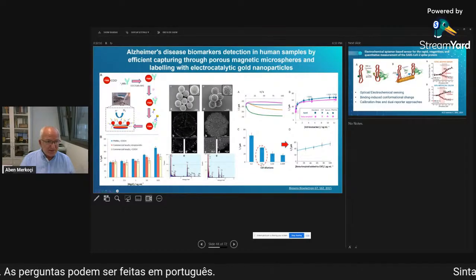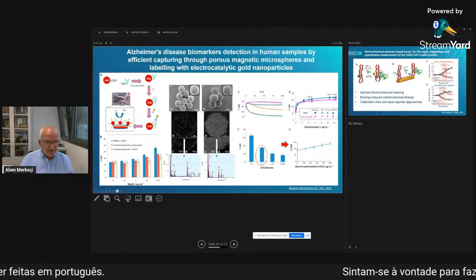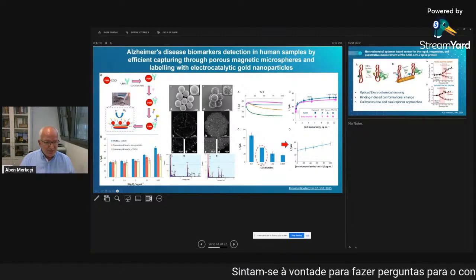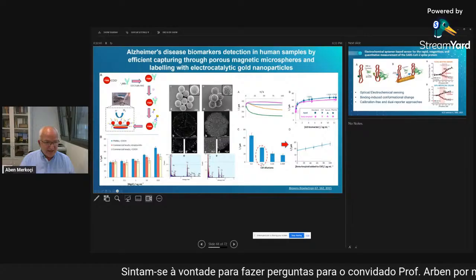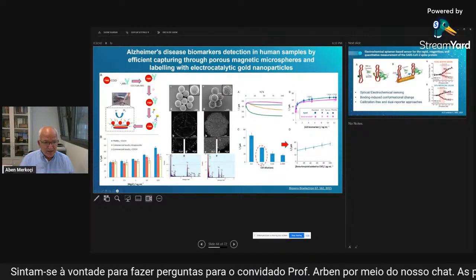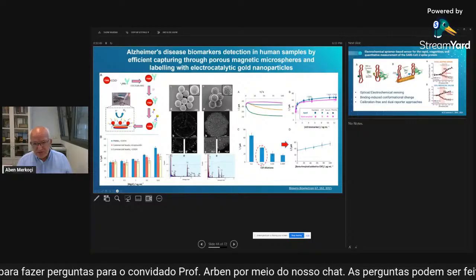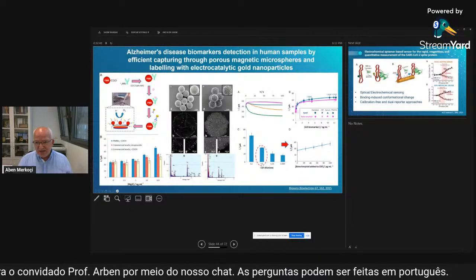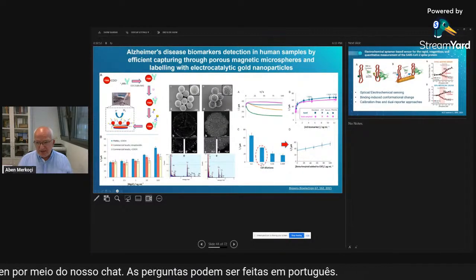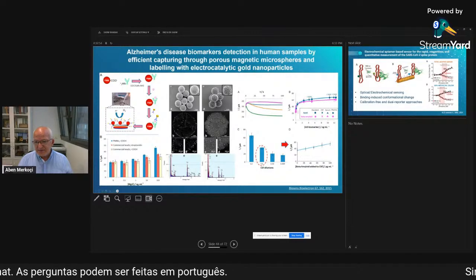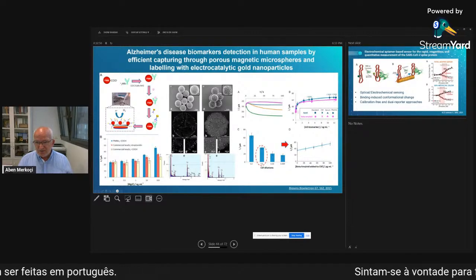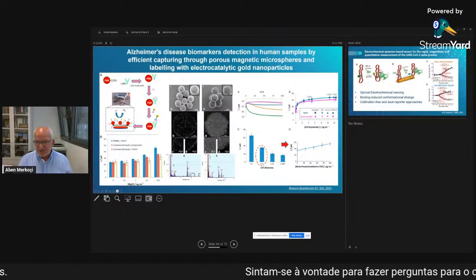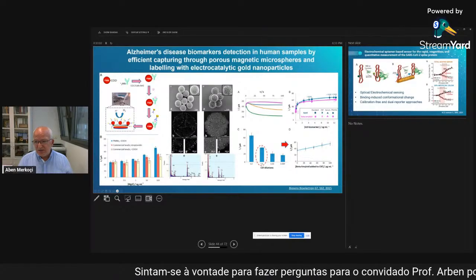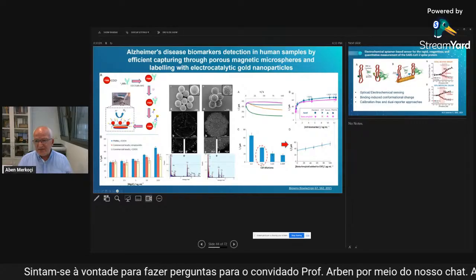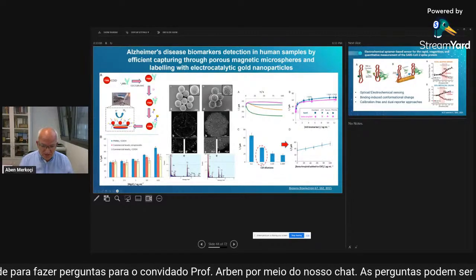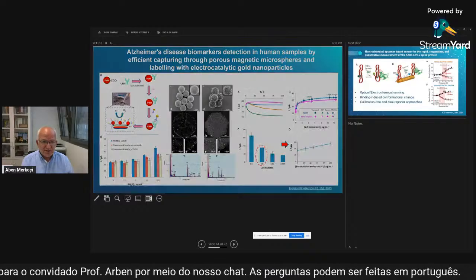So these magnetic microspheres are connected with antibodies against the biomarker. Then we have a secondary antibody that is connected to gold nanoparticles. And afterwards, we measure hydrogen evolution reaction. And you see here the microbeads that we use, and then the measurements of this biomarker in different samples, and you can see the response of the system. So in terms of the catalytic current for different concentrations of these biomarkers, including a spike in different standard solutions, CSF, serum, and plasma. So this was very, very interesting for diagnostics of Alzheimer.